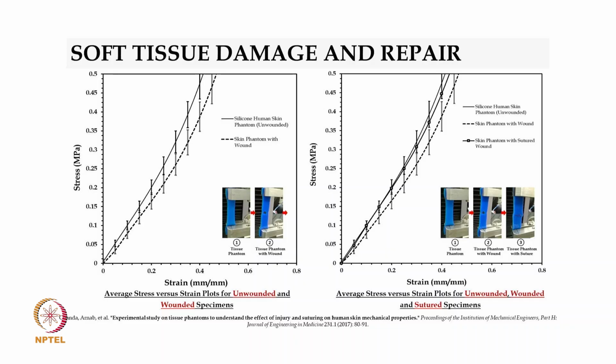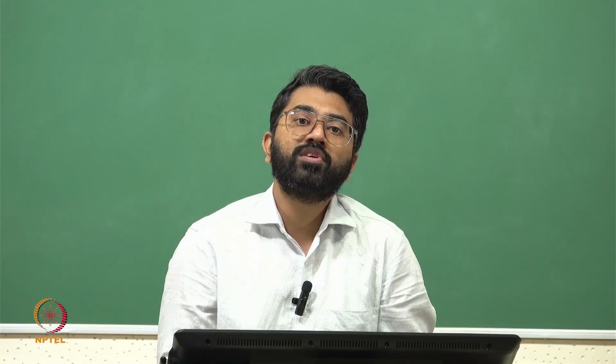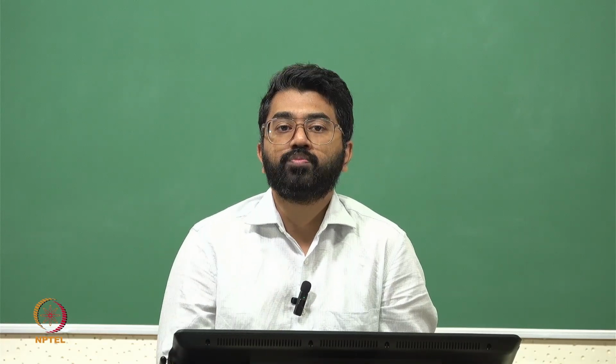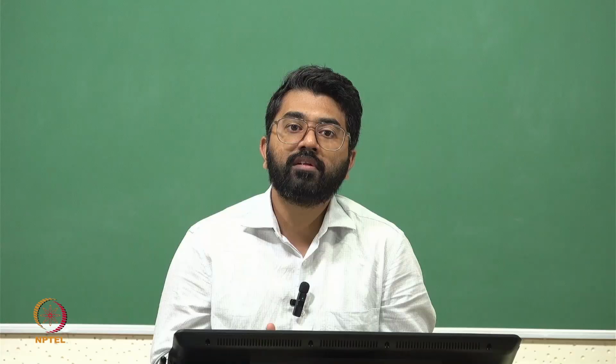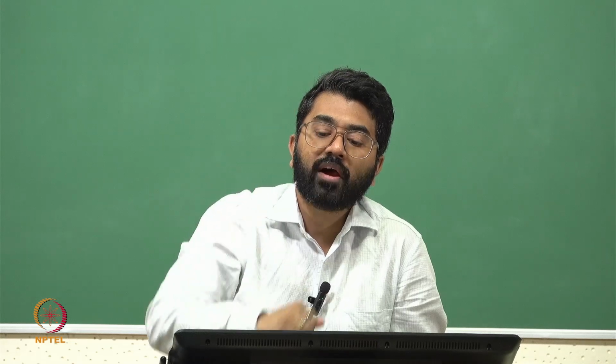So that means with suturing, the overall material property of the skin becomes much more stiff than its natural version, which is also intuitive because you are placing a suture material which is much harder than the actual tissue, right? But this was a very clear finding which we got, and we could clearly say that our research results or the methods are accurate, right? So we saw all the sutured specimens showing much higher stiffness.